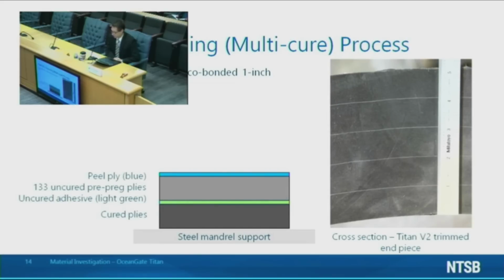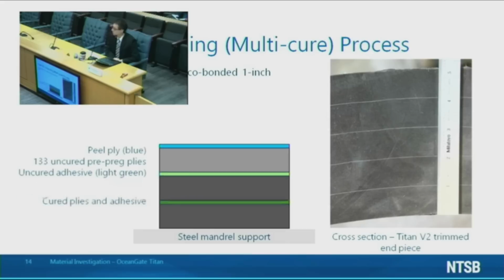The act of stripping the peel ply is intended to create an active surface for adhesive bonding. After peel ply removal, bulges in the hull were removed by grinding. A layer of film adhesive was applied, followed by another inch of pre-preg, capped once again by a peel ply. The assembly was once again sent to the autoclave for curing. This process was repeated until a nominally 5 inch thick hull was produced.